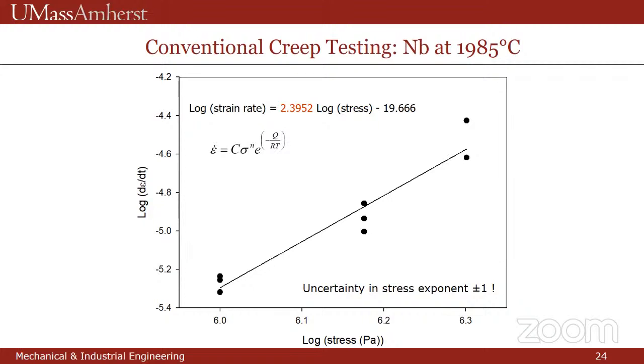And these are typical results for pretty good measurements. These were done in a national laboratory in Japan. And you see that you get a nice fit. The points correlate nicely to a line that fits the functional form for this power law creep. And you see the scatter that gives you an uncertainty in the stress exponent of plus or minus 1. So this is not an uncertainty in the creep rate of a few percent. This is an uncertainty in the exponent. So the variation is huge.